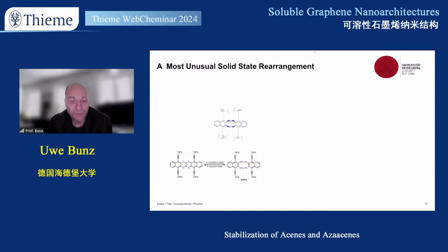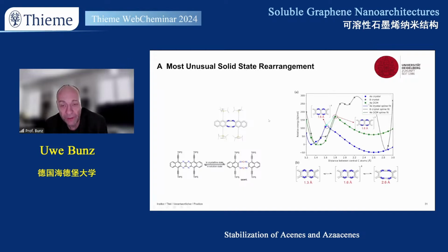So in collaboration with Andreas Dreuw, we did some calculations, and what turns out is that the crystal packing itself actually basically forces this type of arrangement, which is very unusual.